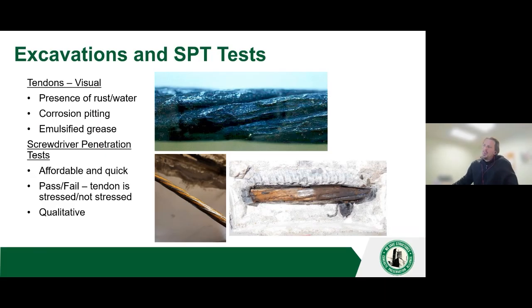Like I said, once we open up a tendon, we want to be very careful to document and take a good look and see if we've got presence of water and rust. Definitely if we've got corrosion, pitting, lost cross-section, even if the tendon isn't broken, and then emulsified grease. So what happens over time is that if air or water gets inside of that strand, the grease will get very dry and kind of waxy.